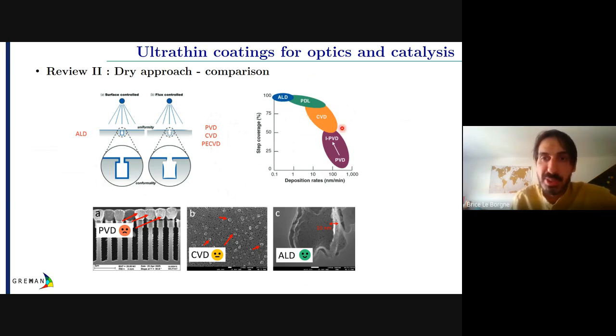There is this interesting graph often used in the ALD community. You can have very high step coverage with ALD or PLD. But of course, it depends on the deposition rate you want. So you have less step coverage with PVD, but you go very fast. So you can also consider using PLD or CVD if necessary, right?